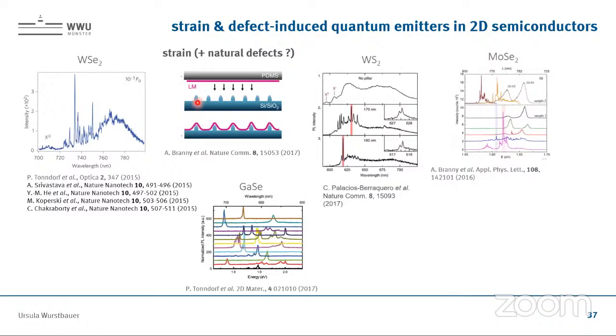However, if you create these little pillars and place a 2D material on top, you will create some strain around these pillars. And then you see now for 1, 2, 3, 4 different materials, tungsten diselenide, tungsten disulfide, molybdenum diselenide, and gallium selenide, that you have these little peaks here. This peak, this peak, this peak, this peak, this one here. And those peaks are all single photon emitters. So now they can be somehow placed.